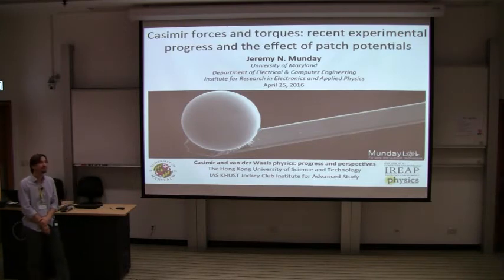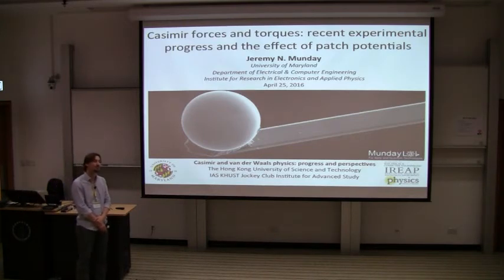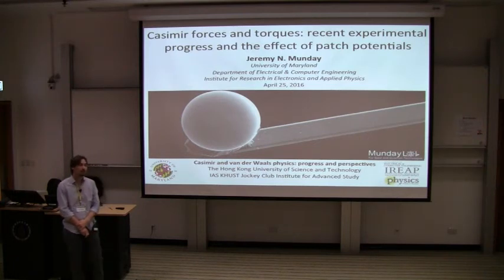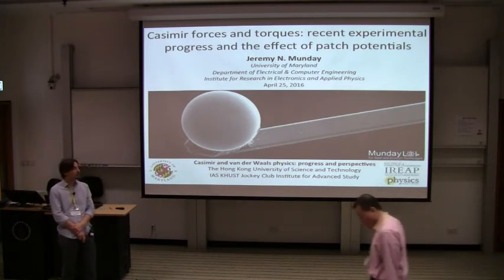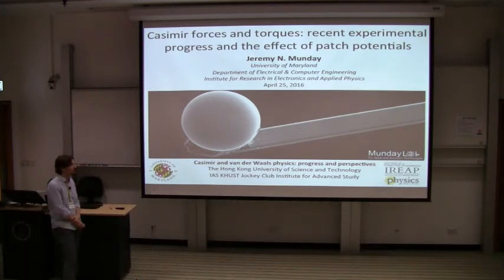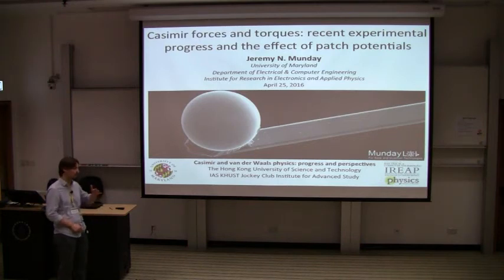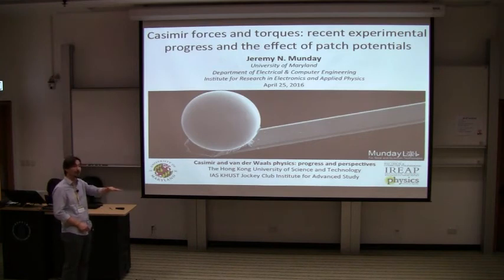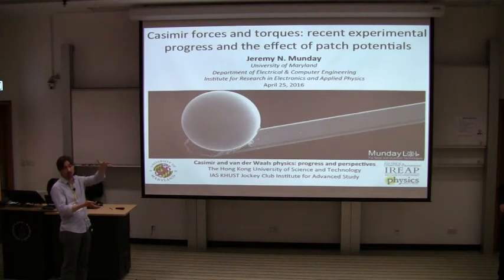Okay, now, most rod-like molecules that I know of are very flexible in direction. Isn't that hard to take into account when you're measuring torque? Or perhaps you have molecules that are stiff? Yeah, with these liquid crystals, they're fairly well characterized, and you can make them so that they are basically in plane, depending on how you coat the surface. So we're making them in plane on one of the surfaces, and then they will continue to be in plane throughout the bulk of it until we get to the other surface.